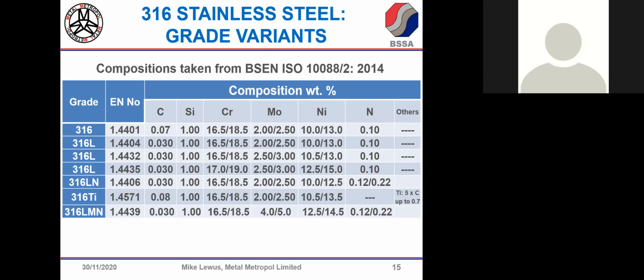It's also worth reminding you of the expensive elements like chromium, molybdenum and nickel. Although there's a lower and an upper spec limit on all these grades, the mills have got tight enough control on the grades to ensure the amount is very close to the lower spec limit. Because obviously if they're producing hundreds of thousands of tons, that would be money thrown away if they always pushed it to the high limit. Money's obviously important to everyone, and if they can put less of those things in, they will. I mean, that's the main thing, is that it is at least within specification.